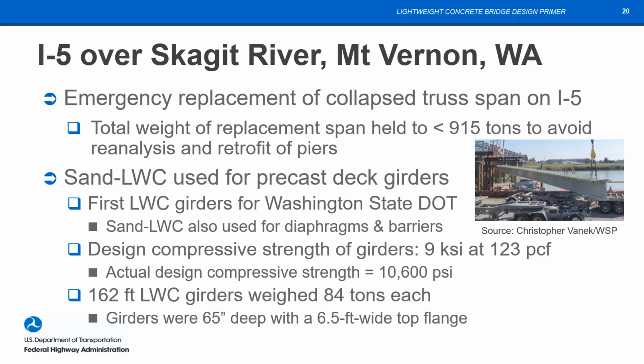So the team that won, led by WSP on the engineering side, came up with the use of a sand lightweight concrete deck girder system. And that was the first time that lightweight concrete girders had been used by Washington State DOT. The design compressive strength was 9 KSI. That was a specification, but the actual compressive strength, figured on the statistics of the compressive strengths in production of those girders, came out to be 10.6 KSI. So it was a high strength mix. It worked well for this, and those were about 162 foot long girders.